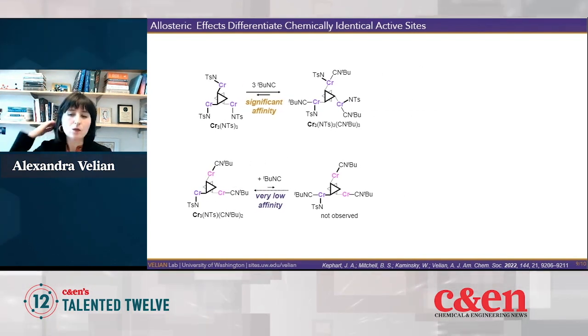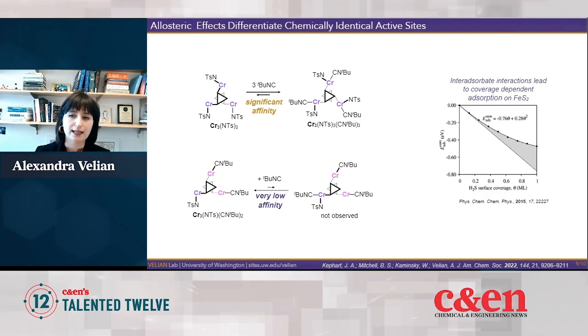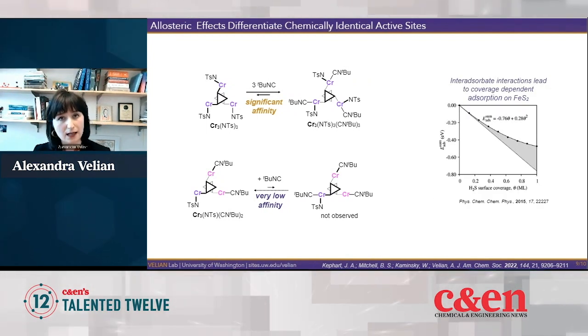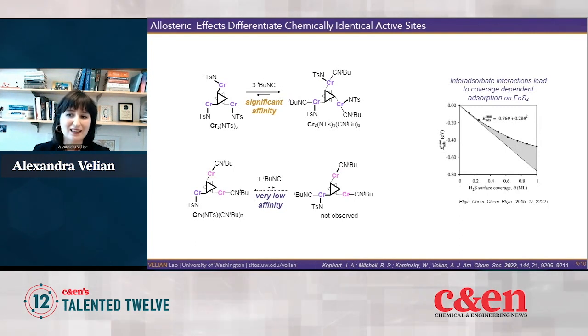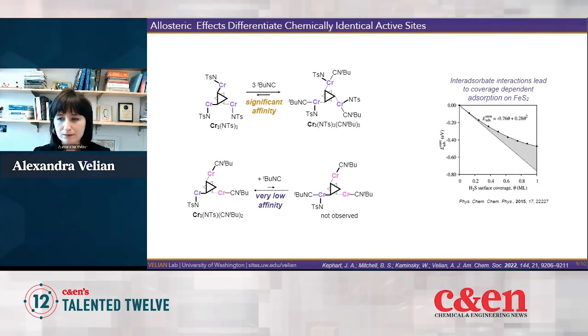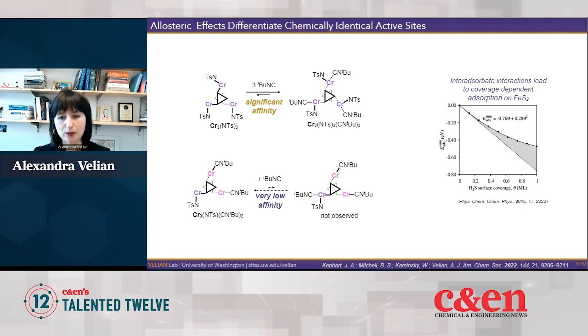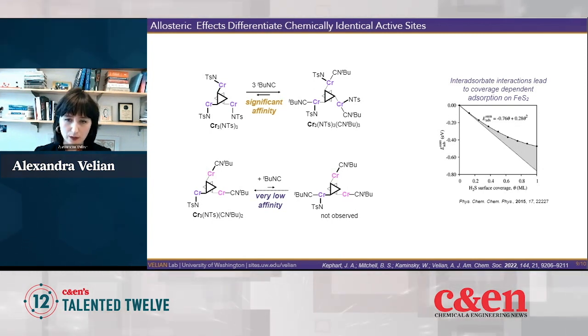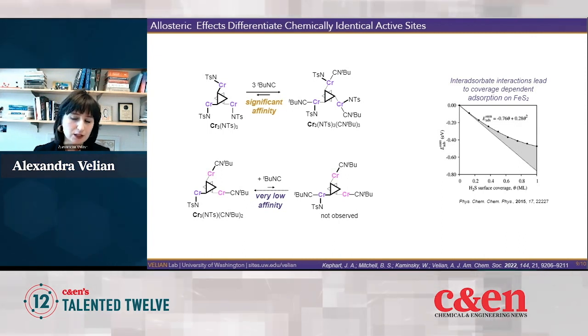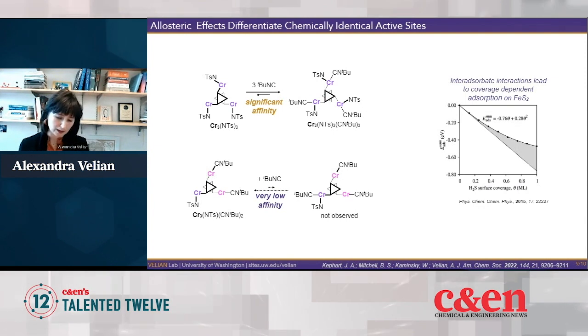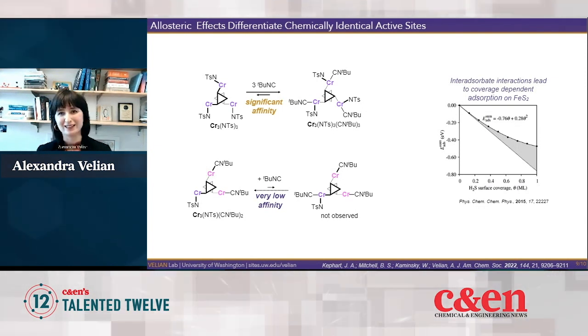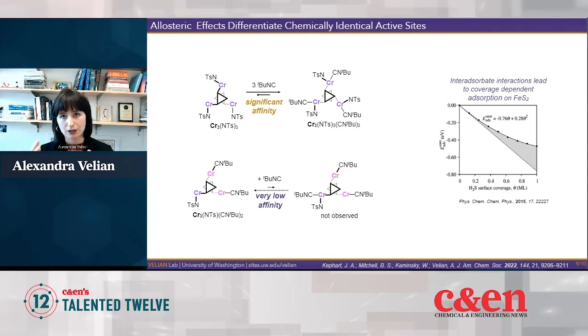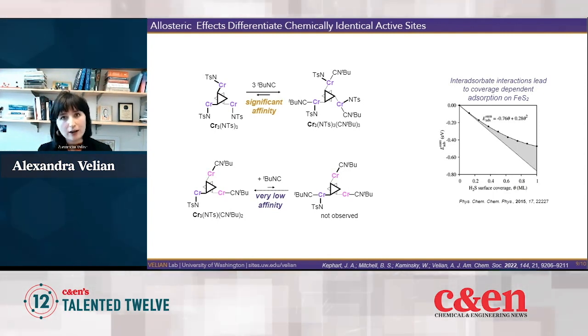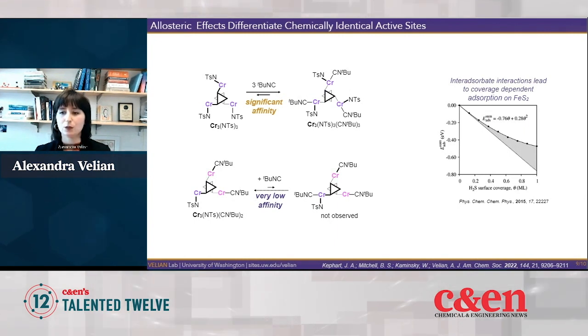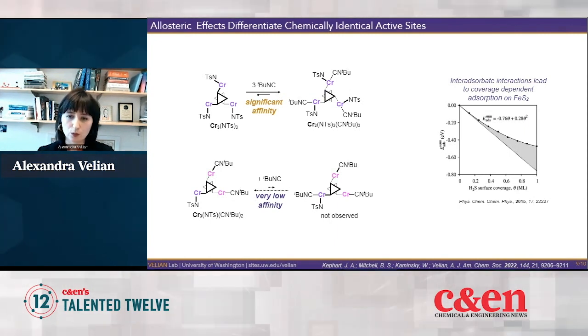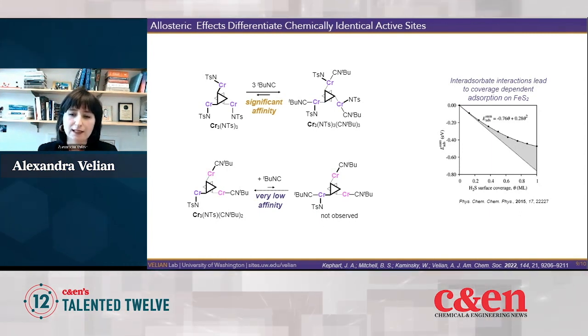And in many ways, what we observe here is really similar to these interadsorbate interactions that occur on many surfaces, for example, iron sulfide, that lead to coverage-dependent adsorption of substrates. And so we can capture this in a molecular system, but with atomistic insights. And so just to conclude, I want to show you one of the ways in which we think that this allostericity that occurs on the surface of the cluster can be harnessed for various purposes. We think a lot about that in the group, but just one recent way in which we've collected on this is to